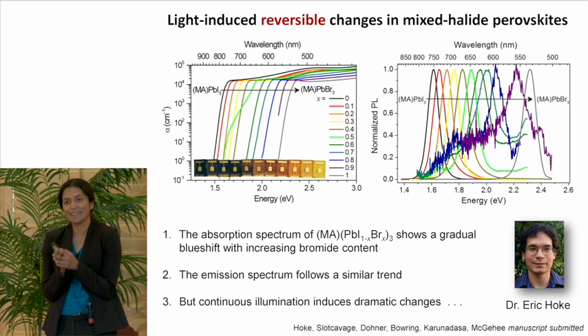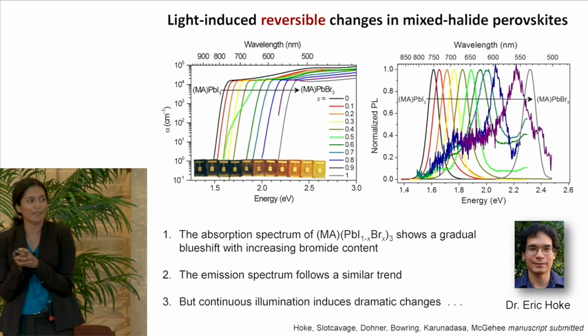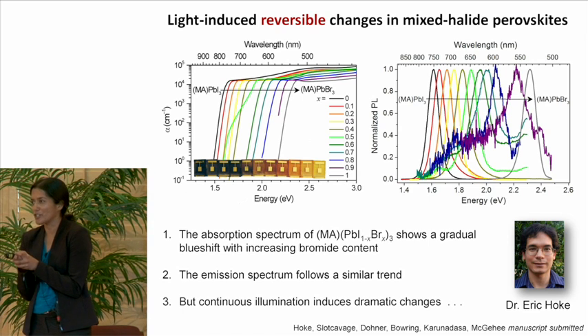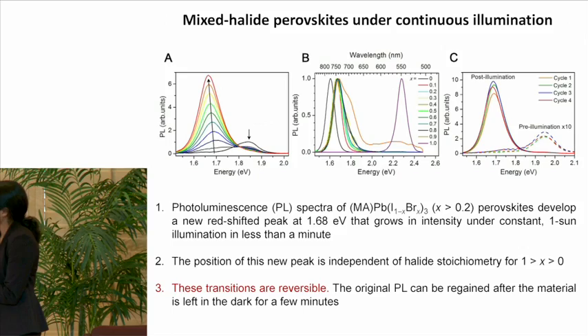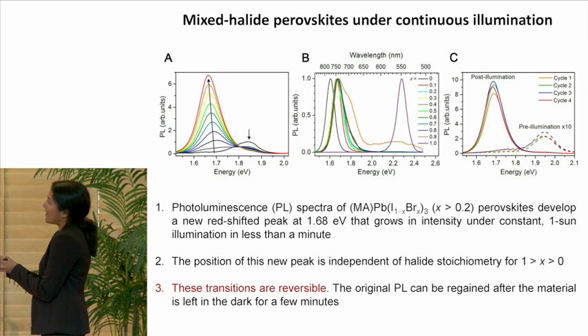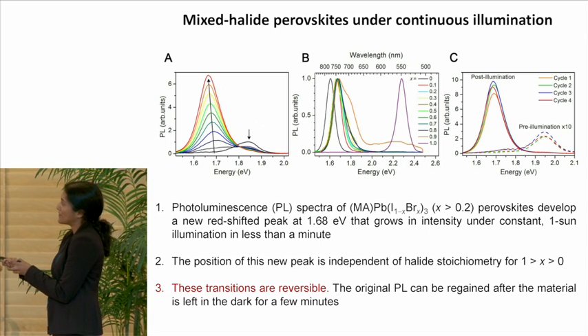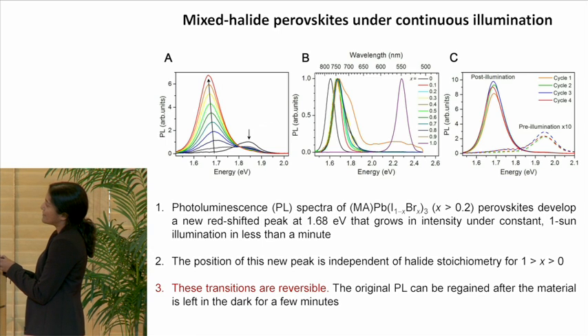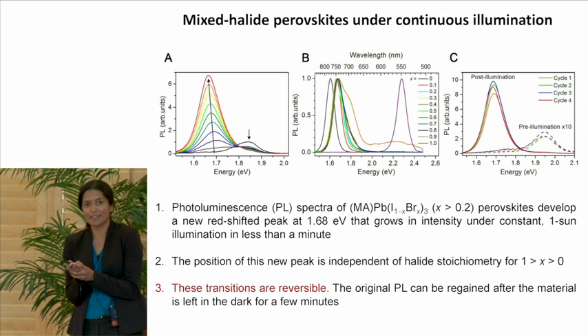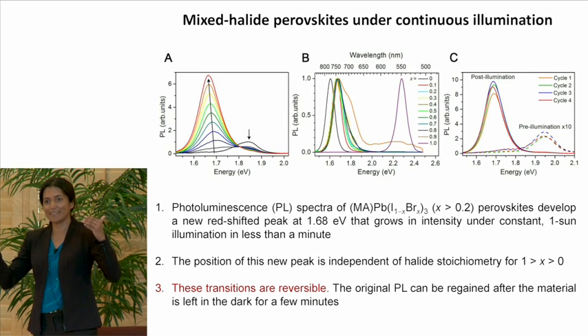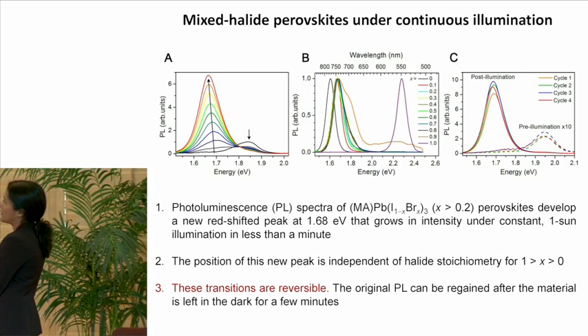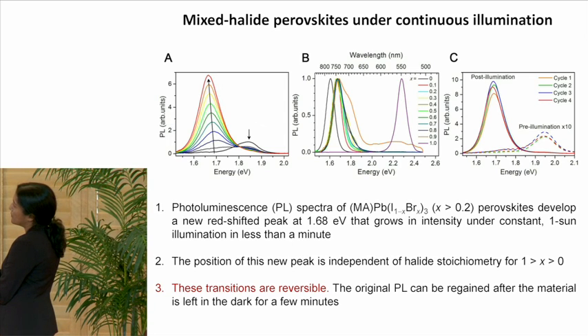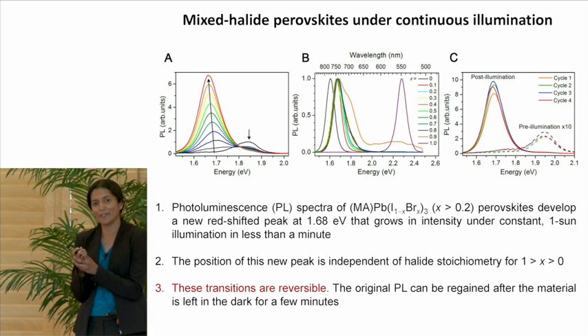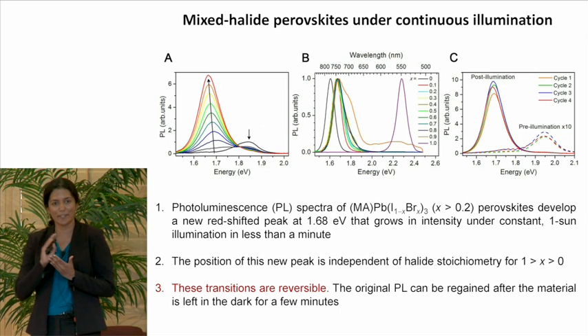But Eric found that if he kept shining the light on these materials, just at one sun illumination for about a minute, this material changes dramatically. So he finds that as he keeps illuminating these materials, the initial photoluminescence starts to die down. And a new photoluminescence band starts to grow in that gets very high in intensity at around 1.7 eV. Curiously, it doesn't matter where the initial photoluminescence band begins, they all merge, and the eventual photoluminescence arises from this band at 1.7 eV. So the all-bromide material does not show a shift in PL, the all-iodide material does not shift, but every other intermediate stoichiometry changes and moves to this material that emits at 1.7 eV.